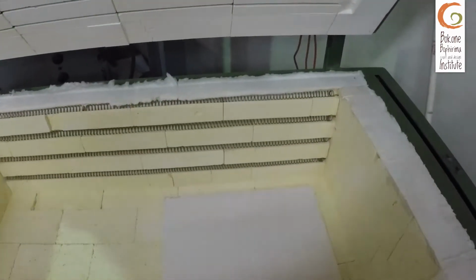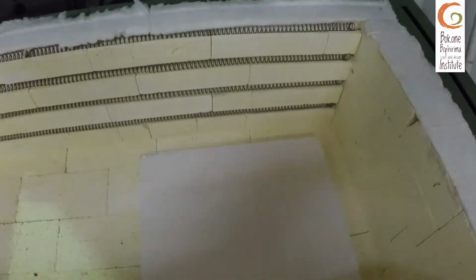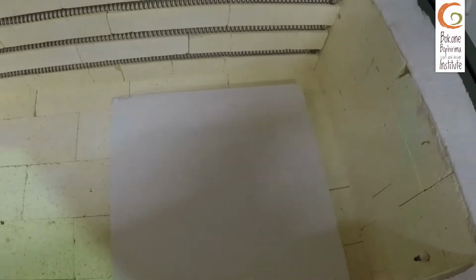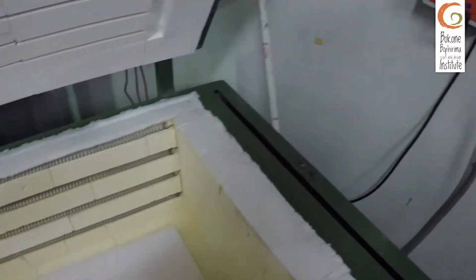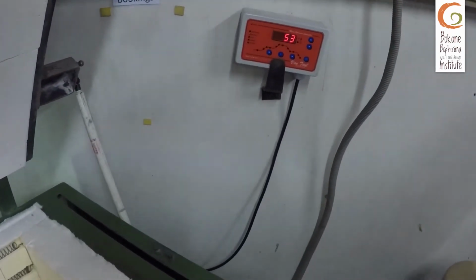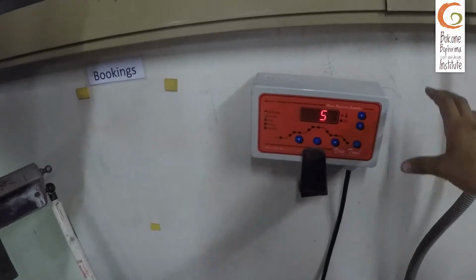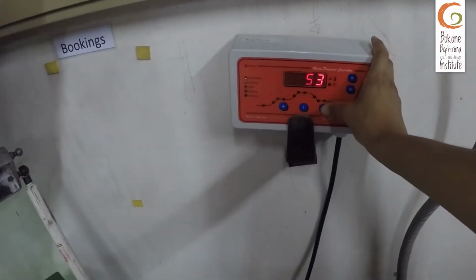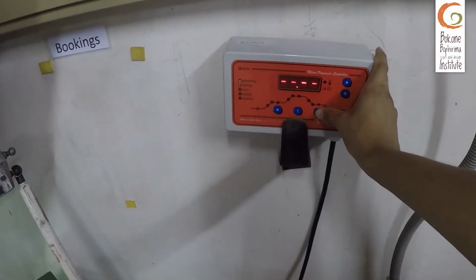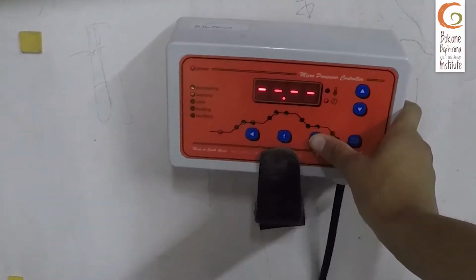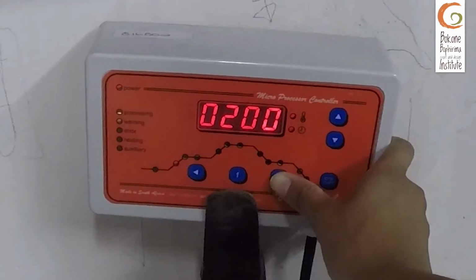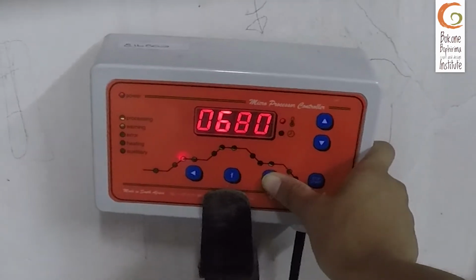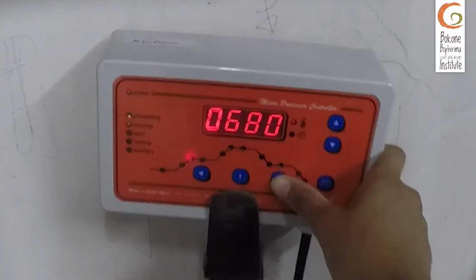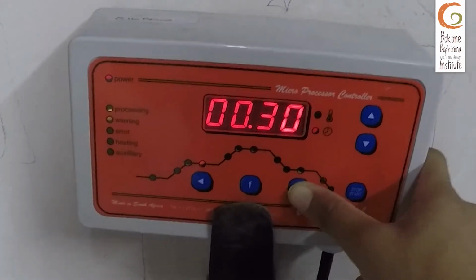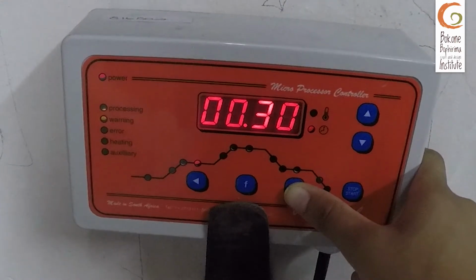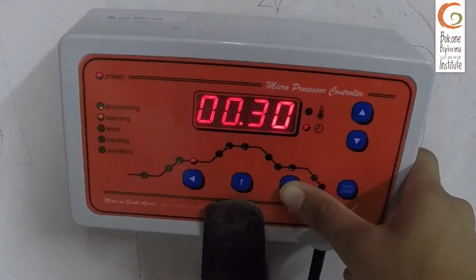On our program, we start with the temperature of the kiln, which is 53 degrees. The thermostat reads 53 degrees, and we move on our right side with the arrow pointing to the right to the next step, which allows you to start immediately. And we go up the ramp at 200 degrees per hour to 680 degrees, and we hold it there for 30 minutes to allow the glass to expand properly.